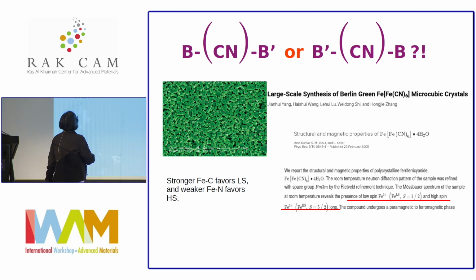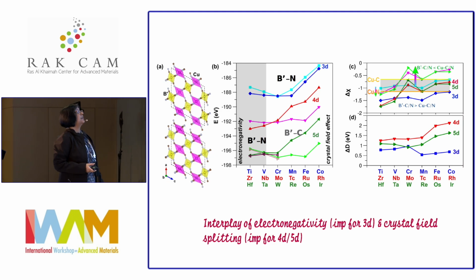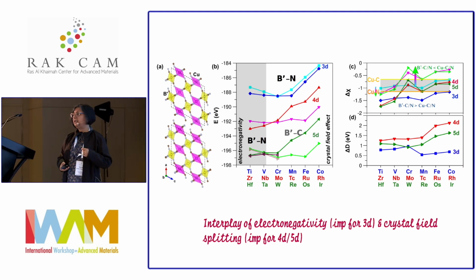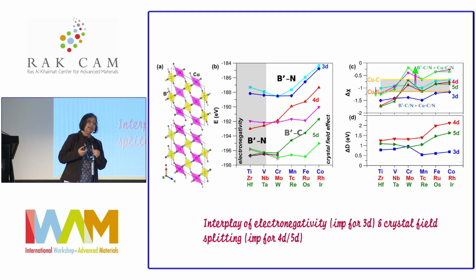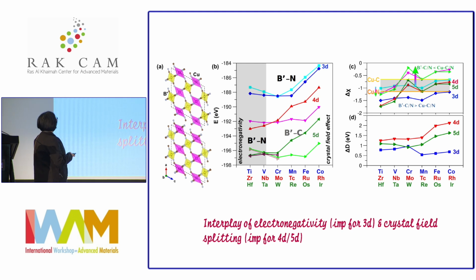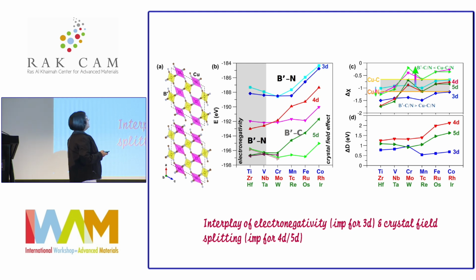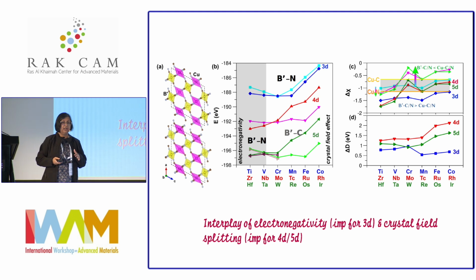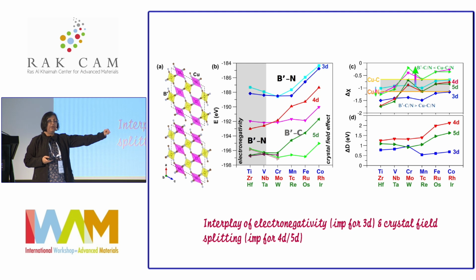So the first exercise was a simple exercise where we basically calculated the formation energy considering the C linked to copper and B prime linked to nitrogen and vice versa, and compared their energy. And what we find is pretty interesting. In the 3d series, with the exception of chromium, the B prime N is always favored. That means the carbon likes to link with the copper, while the N end of CN likes to connect with the other transition metal, namely the B prime.